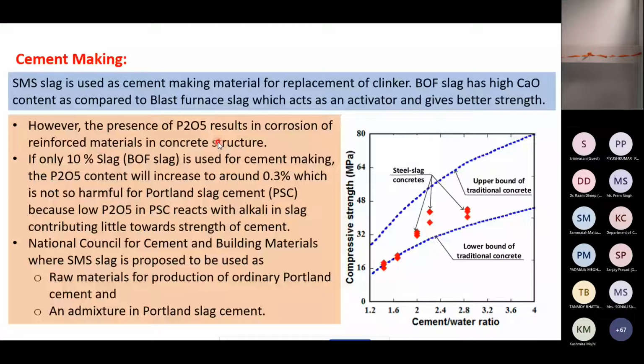But if the P2O5 content is very less, so while manufacturing this steel only, if you have maintained the proper content of phosphorus and then maintain the least amount of P2O5 in the final slag, then it can be easily used. If only 10% slag is used for cement making, the P2O5 content will be increased around 0.3%. So what these cement making industries are doing, they are taking up the slag and mixing, and they are utilizing a very limited amount of the slag, so that the final amount of P2O5 in the final product is 0.3%.